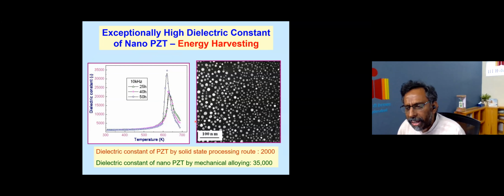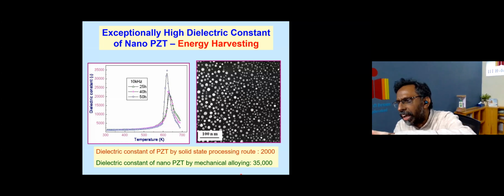Usually a PZT material has a dielectric constant of the order of 2000. The moment I make it nano, like this, each particle is very small, 10 nanometers in size, and its dielectric constant is 35,000. What is the advantage of this? We have seen that once the material has such a large dielectric constant, you can ensure that piezoelectric materials have a special property that if you compress the material, it produces electricity.